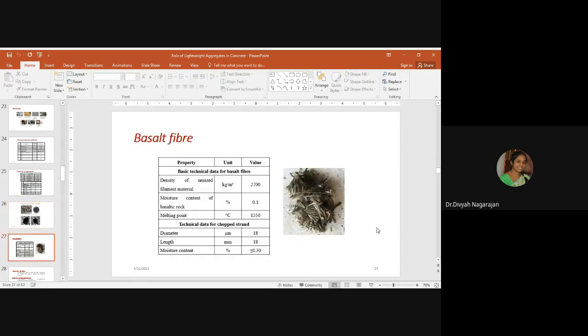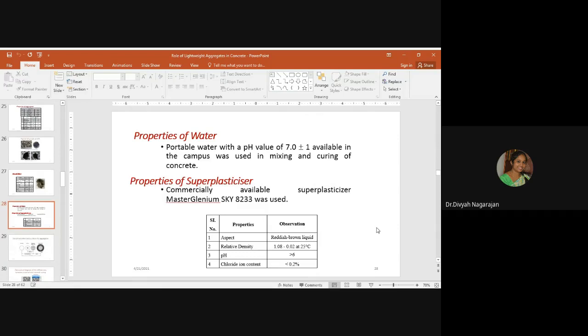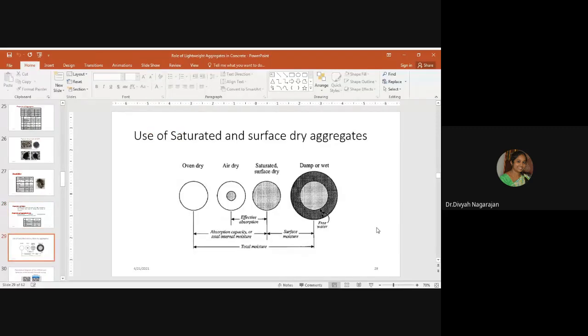Basalt fiber. Basalt fiber of length 18 mm was used for the investigation. Water, potable water available in the laboratory, was used, and the superplasticizer. The superplasticizer Master Glenium Sky 8233 was used in the investigation because it has excellent properties that enhance the workability of the concrete. Now coming to the point, use of saturated and surface dry aggregates. The water absorption of the sintered fly ash aggregates was found to be nearly 15.4%, which is considerable, and which is an area of concern.